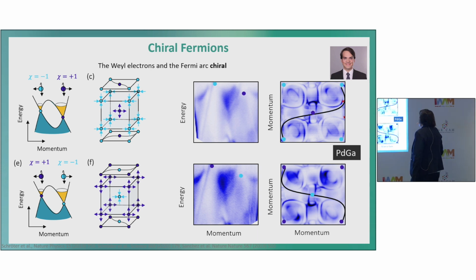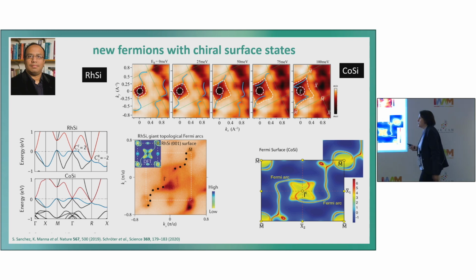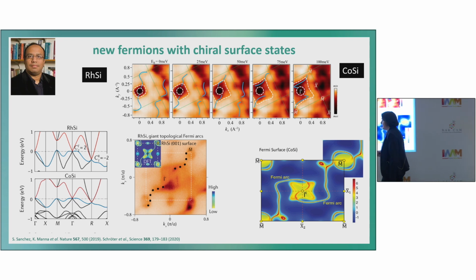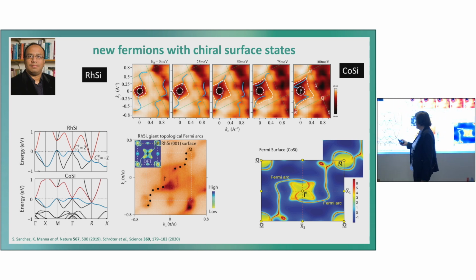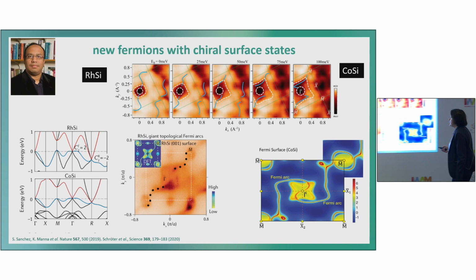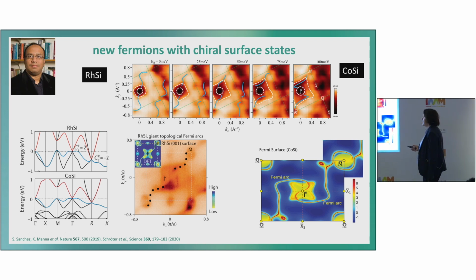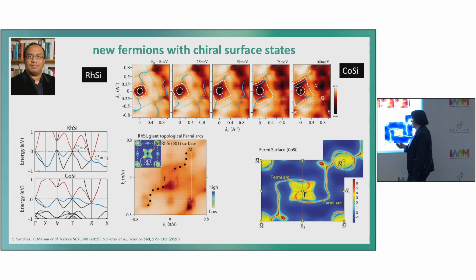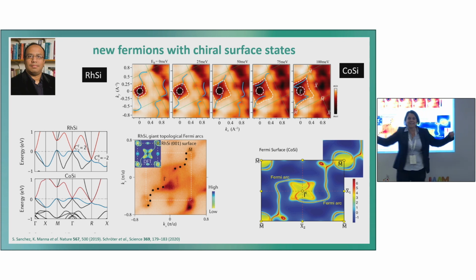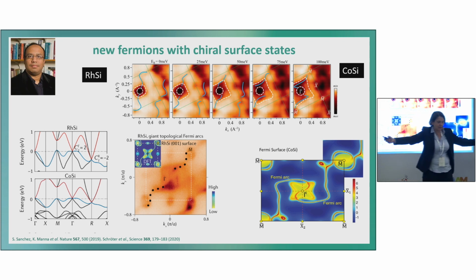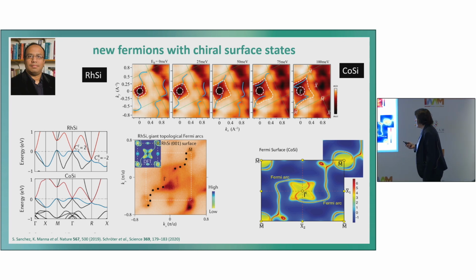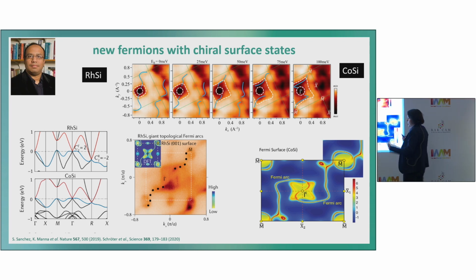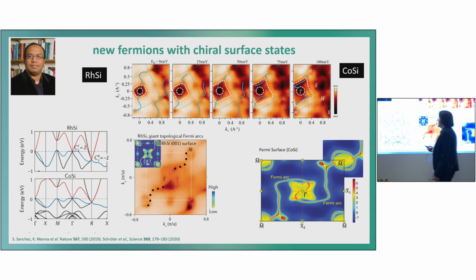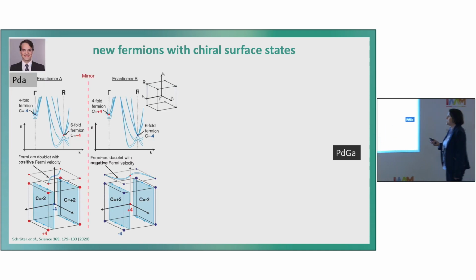So this was done on palladium gallium, but we had another collaboration with crystals of rhodium silicide and cobalt silicide. They also have these points at different energy, and with Hassan's group they could nicely show that we have these Fermi arcs, which are chiral. The other thing is that these Fermi arcs go all over the Brillouin zone, so the Weyl points are so far from each other that they spread over the whole reciprocal space. Therefore, there is no way to annihilate them. They are at different energies, and they are all over the Brillouin zone. The band structure looks quite different, but they are still related via topology in this chiral crystal.